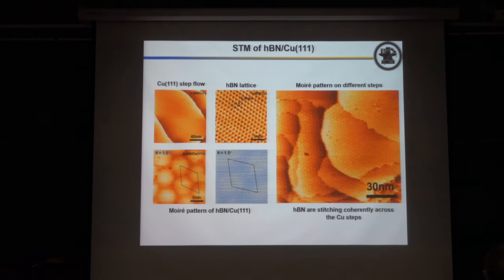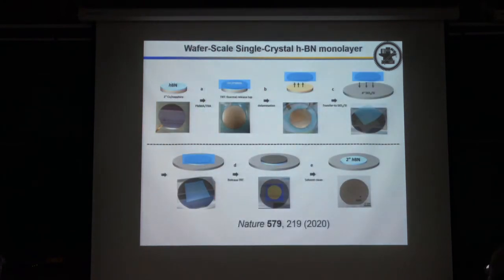Okay. So this is the STM result. You can see very clearly the step flow of copper 111, and also the moiré pattern of boron nitride with the copper lattice. You can also see the moiré patterns are aligned across the step flow. That means the boron nitride is stitched together and goes across the step. So they form a continuous film, even across the step. And then we can use some technique to exfoliate the material and transfer it to another substrate.